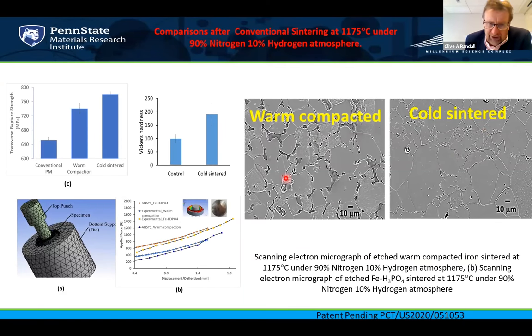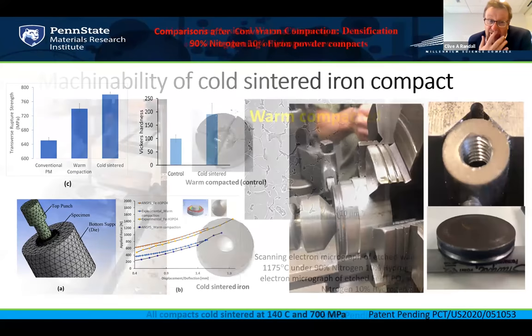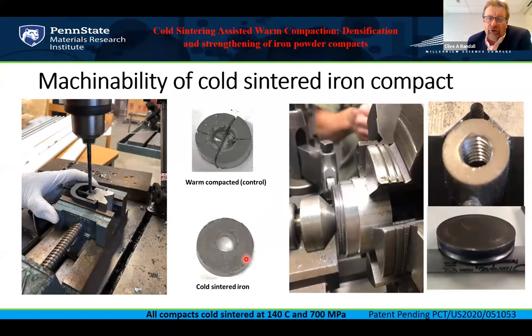And you can also take this process from the warm compaction into a sintered state, a normal firing, after the cold sintered warm compaction process. And these all have superior properties to the normal warm compaction or even room temperature conventional powder metallurgy pressing. Where it is super exciting is that it allows you, even in the green state, to get high density materials that you can then mill.